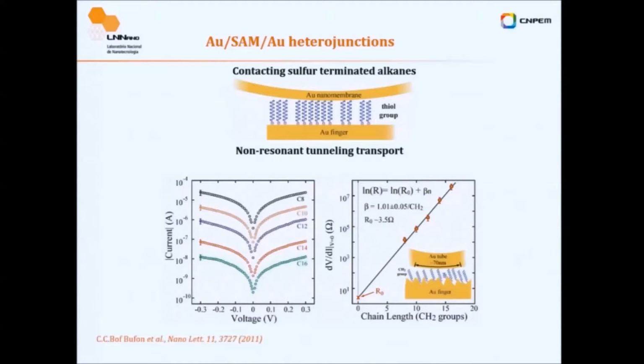So what is the limit of this technology? The roughness of your surface and the linear size of your molecules. Let's assume you have a 2 nanometers roughness here, 2 nanometers roughness here. Basically, you cannot measure a 1 nanometer layer. Otherwise, you have a short circuit. It would be like needles inside of your organic layer.